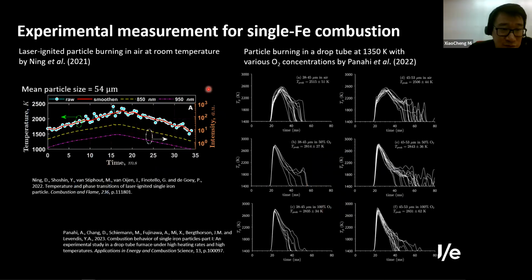The most important result that we can use to compare with our model and hypothesis is the temperature history of a single particle burning in different conditions. This is the one that Ning and his colleagues obtained. This curve right here is the temperature, for a particle size around 54 micron, in air. The surrounding gas temperature is just room temperature, so it is considered a cold surrounding. You can see the peak temperature goes up to around 2400, below 2500.